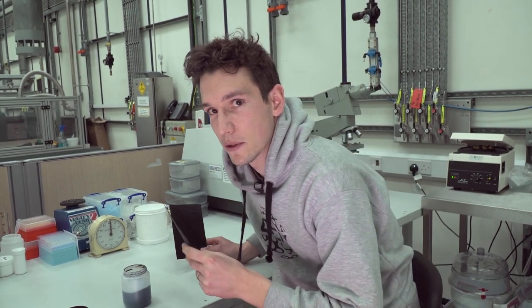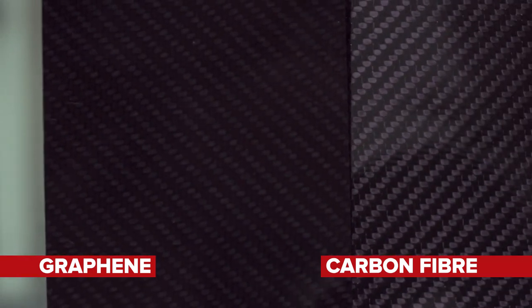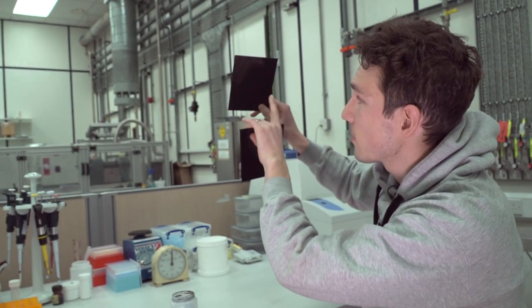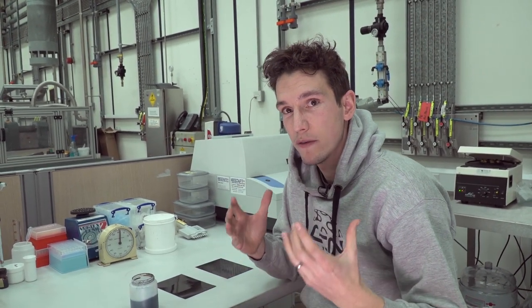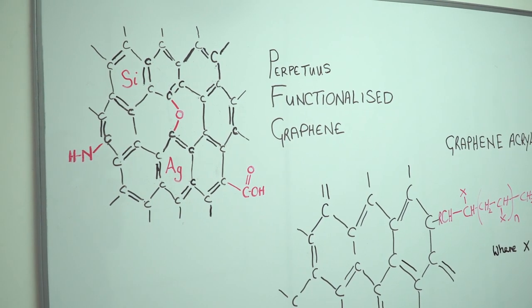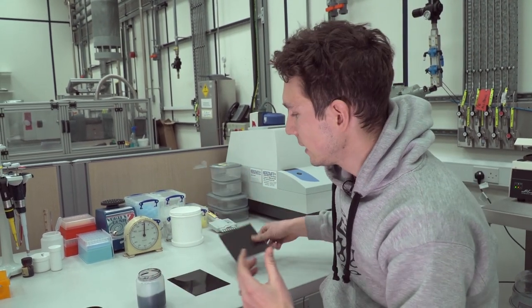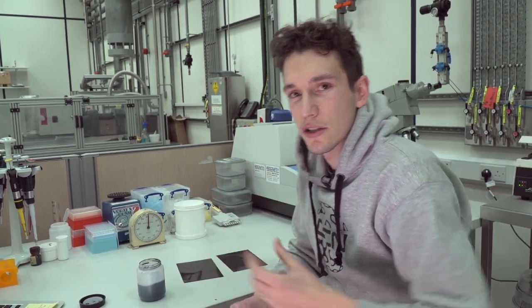We're going to quickly see the difference between the two. If I hold them up to the light, you'll see that in the graphene-impregnated carbon fibre, almost no light permeates through it. Whereas in the normal carbon fibre, all those areas of light are actually potential weak spots because there are no fibres there, only resin. On this one, the graphene is dispersed evenly throughout the resin, making it a much more uniform piece of material. That's because the graphene itself improves the strength of the resin by chemically bonding to both the resin and the carbon fibres. Those bonds act like little hooks and increase the so-called interfacial shear strength. On traditional carbon fibre we have two separate components — resin and carbon fibre — whereas with graphene it's bonded together into one uniform and much stronger piece of material.